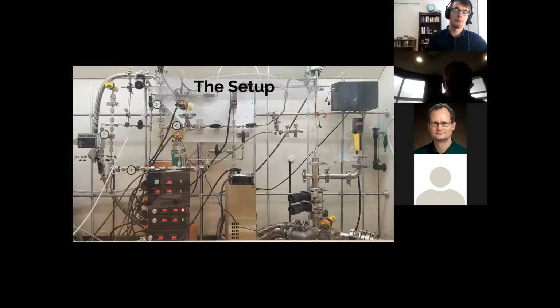This image is the plasma reactor setup at NDSU, and it's gone through many iterations. The original apparatus was made by Todd Pringle and was used to create silicon nanocrystals, and it has since been adapted and expanded to make the silicon carbide nanocrystals described here. So the basic working principle of the reactor is that a precursor gas is fed into a bubbler, or an organometallic bubbler, where the precursor sits. So that's where the TMS is.